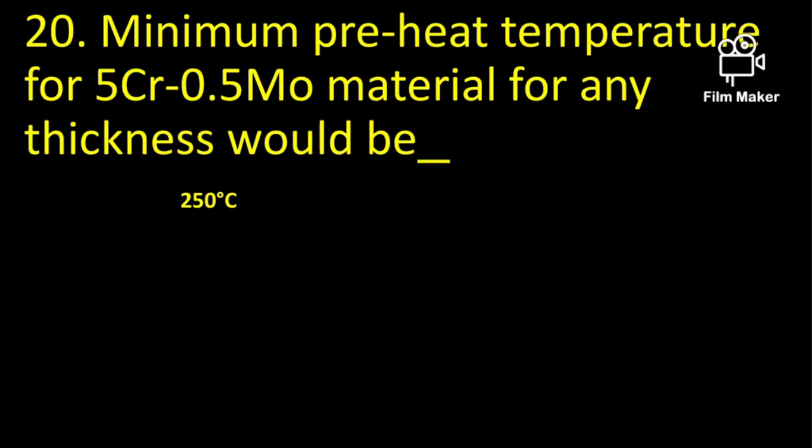The minimum preheat temperature for 5 chromium 0.5 molybdenum material for any thickness would be 250 degrees centigrade.